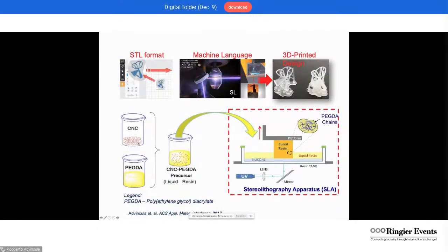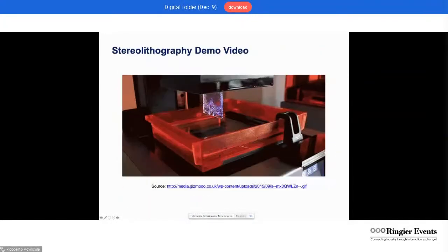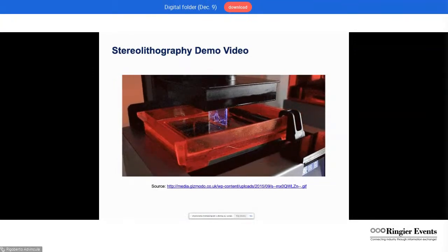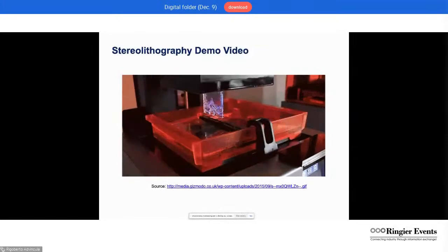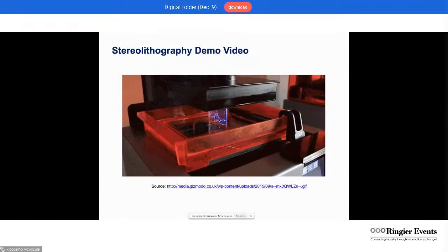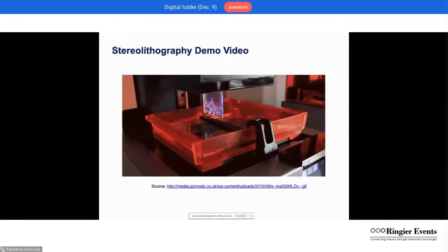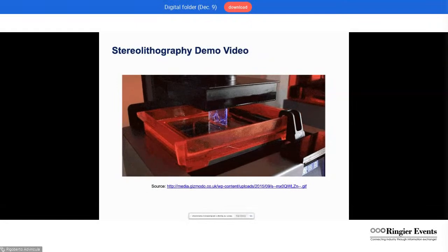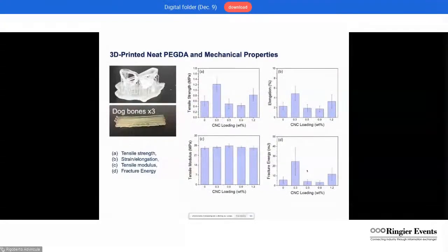So when we mix CNC with PEGDA, you can see that this material can then be used for VAT SLA photopolymerization to produce parts. So by way of this movie, this is a Formlabs printer where we added the nanocellulose with the PEGDA resin or a formulated resin, and then 3D printed the object by photopolymerization, which you can see building up here on the elevator stage. So we have measured properties, and indeed, even at as little as 0.3 weight percent loading of the nanocellulose, we get a doubling of the tensile strength, the elongation at break, or a dramatic increase in fracture energy. However, the tensile modulus is retained in a variety of compositions.